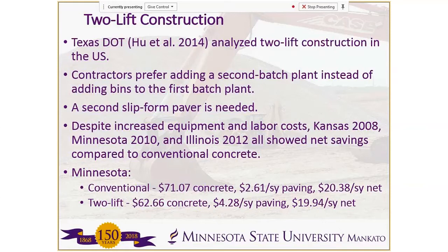Also, with this type of construction, you need a second slip form paver. So the equipment cost is going to be increased, labor costs are going to be increased. However, overall, these constructions still came out cheaper compared to conventional concrete because you had a lot of savings in the material costs, and that offset the increased construction costs. So, for example, in the Minnesota construction, the conventional concrete cost about $20.38 per square yard, whereas the two-lift construction was $19.94. So it actually came out cheaper despite the increased construction costs.